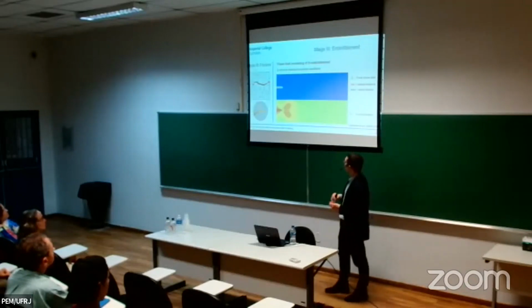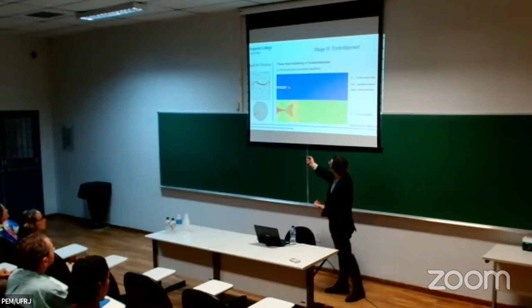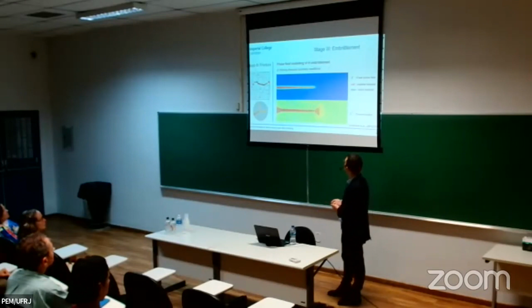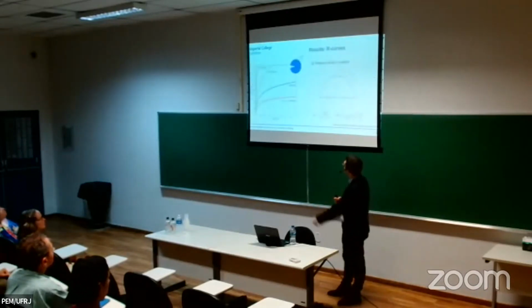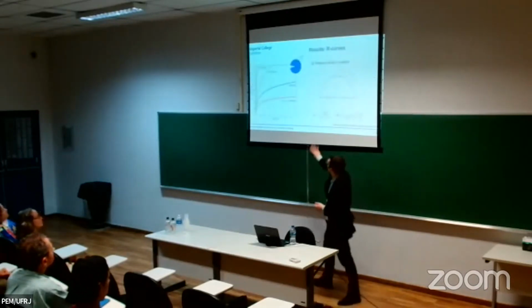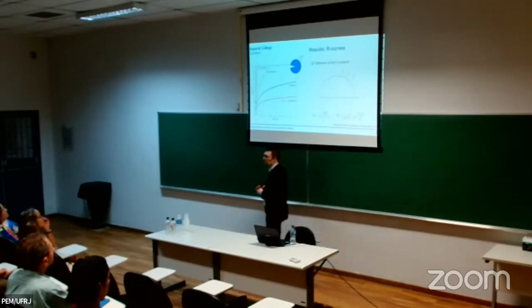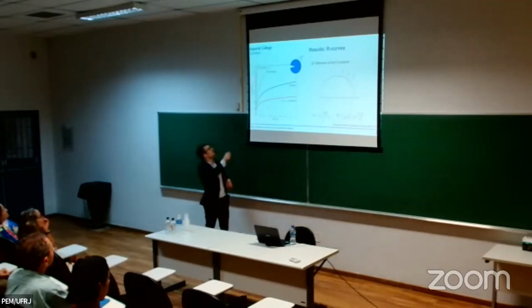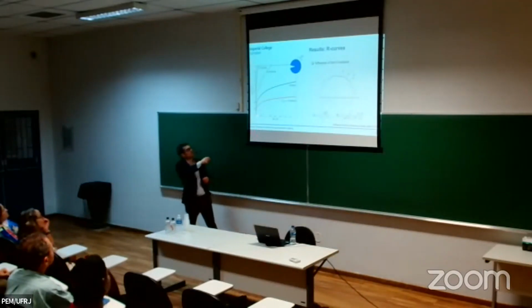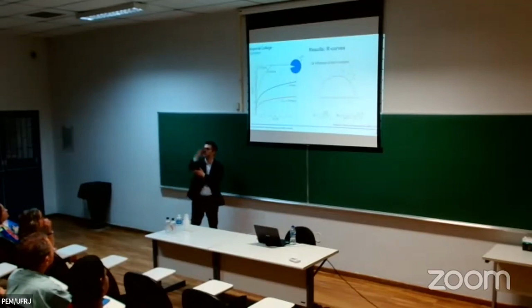The way we choose to do it is through a penalty approach. You can see here how, as the crack propagates, the hydrogen concentration from the environment quickly follows. So let me show you some representative results with this framework. What I'm showing here is what we call R curves, crack growth resistance curves. This is a measure of the crack tip's loading conditions, and this is the crack extension. And we see what we expect from experiments, that as you increase the hydrogen concentration, you lower your fracture resistance.